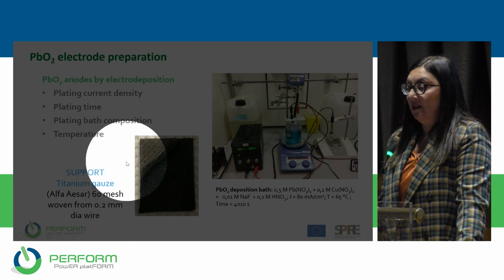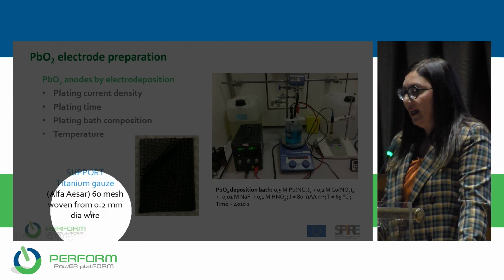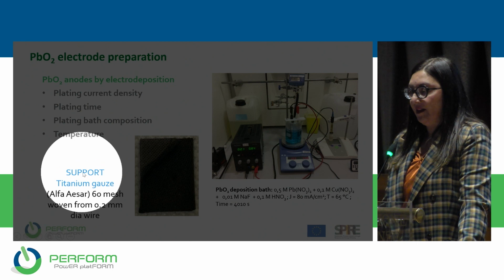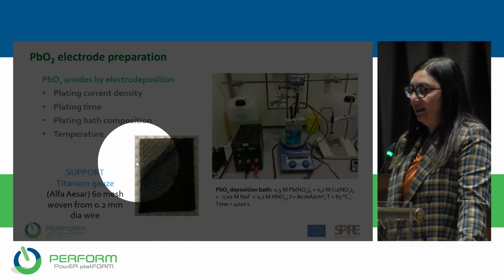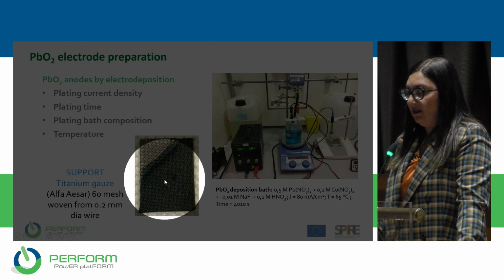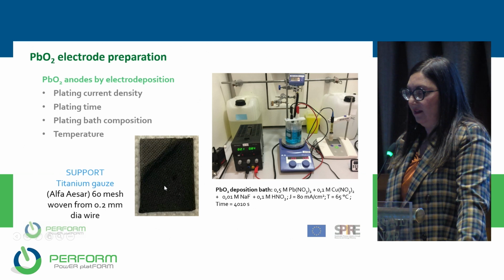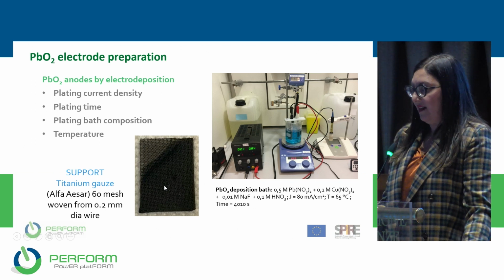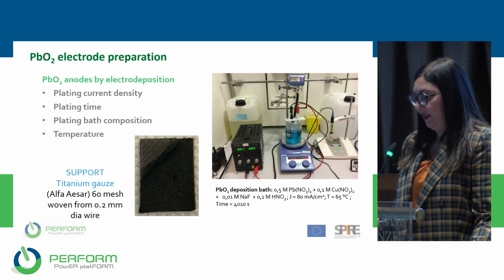The material was deposited on an inert support that was pre-treated, and as support we initially used a titanium gauze, and here is how the electrode at the lab scale appears after preparation.